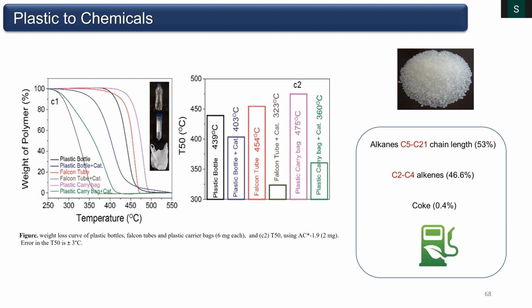And this again can be done. We know the science now, by tuning the surface properties of the material, not only the size and surface area, but also the interfaces, how the silicon and aluminum are bonded, the bond distance. That will allow you to tune the acidity. And if I get an even stronger acidic material, keeping the porosity the same, we may be able to decrease that to an even lower temperature.